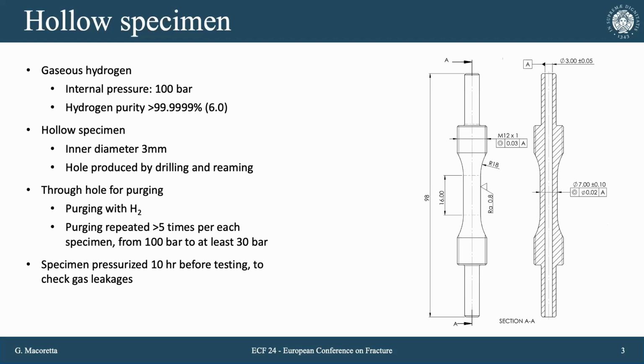We work with a hollow specimen. It's a hollow specimen with an internal hole produced by drilling, and in this case, reaming, with a diameter of 3 millimeters. We introduce gaseous hydrogen into the specimen at a pressure of 10 megapascal, but we can reach even 20 megapascal. We use hydrogen with high purity, research grade purity.